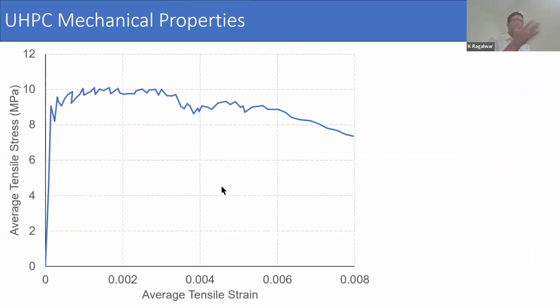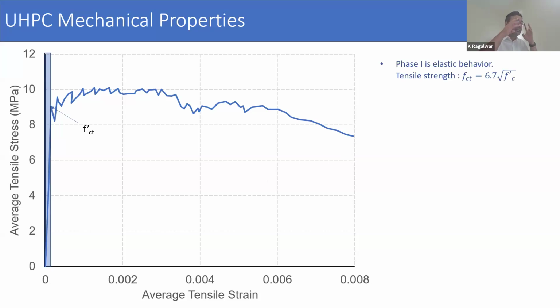Now we look at the unique feature of UHPC, which is its behavior under tensile loading. So this plot here is what is known as the response for uniaxial tensile test. On the y-axis we have tensile stress in MPa and average tensile strain on the x-axis. So the first phase, when we start loading it under uniaxial tensile loading, is we see that there is a straight rise in the stress with increase in strain, and that is almost linear. So phase one is elastic behavior. And generally, the cracking strength, which is the first cracking strength here, where we see a sudden drop, is empirically thought to be equal to this value here.